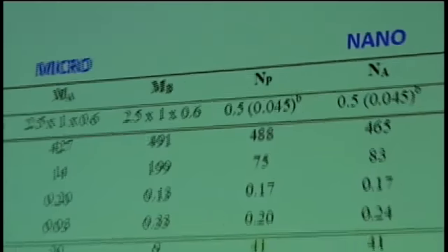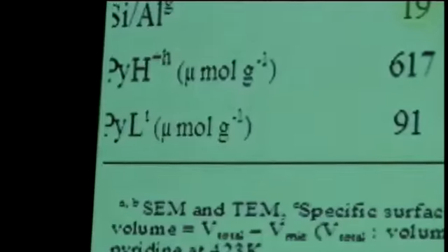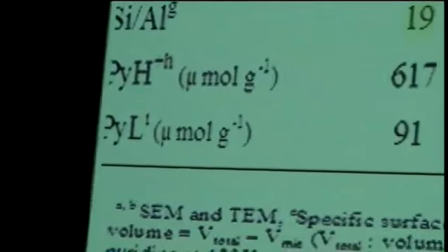And then we will focus, for instance, on the micropore and the mesopore volume. You can see that these materials are of quite a good quality. Okay? When you do the leaching with the fluoride ions, you see that you purify the crystals, so you see the micropore volume increasing. There is basically no addition of mesopore volume, while if you do a basic treatment, then you reshuffle quite a lot, and this has been explained already in a few papers. You reshuffle a lot the pore volume, so you lose microporosity, but you gain mesoporosity. And the story is the same for the nano-sized crystal to a different extent.